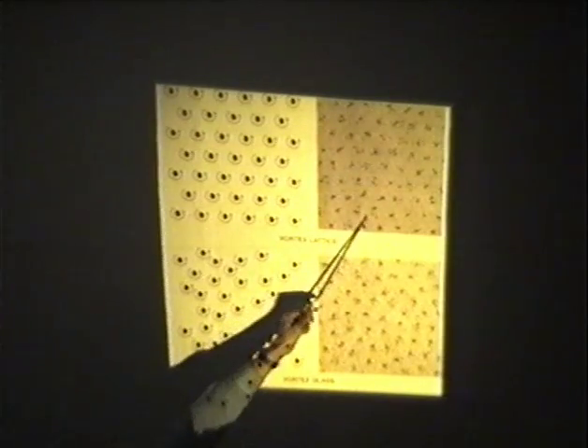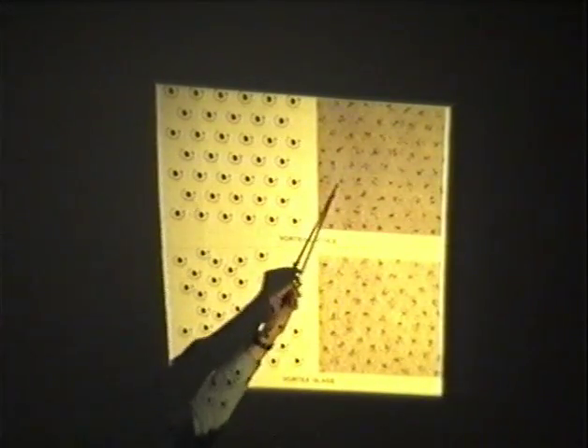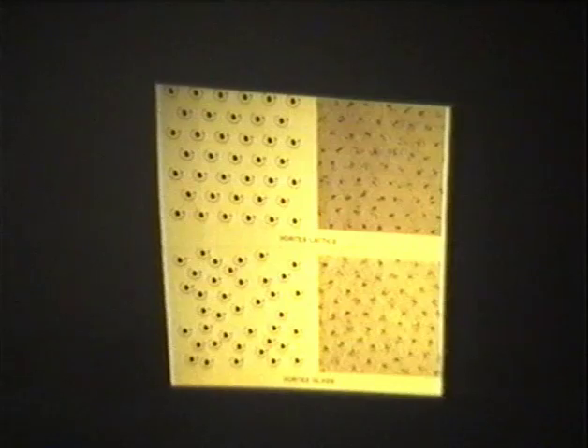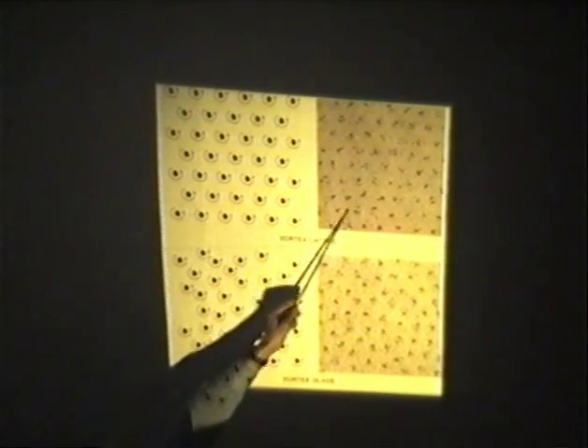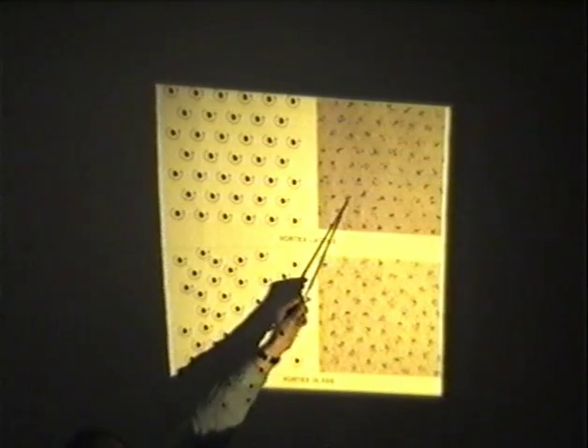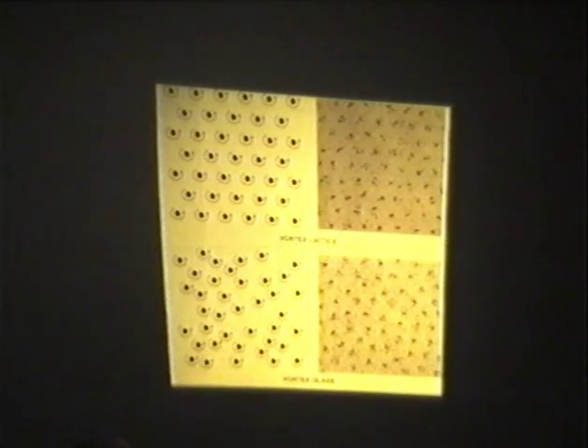And here's an actual picture of the vortices in a metal superconductor. You can dust the surface with a bit of iron powder and it sticks to the place where the material has gone normal, where the magnetic field is, and you can see this nice vortex lattice of vortices where the material has begun to break down, but it still has zero resistance.